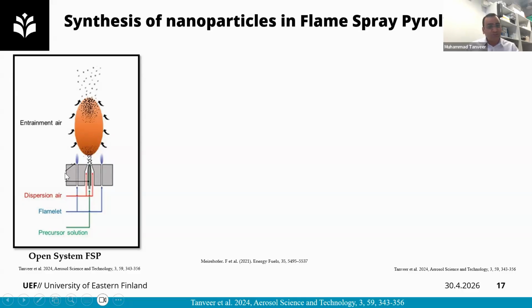Due to this oxygen and the highly reactive, high temperature atmosphere, different gas phase products start to be produced. When the gas phase product concentration is quite high, they become supersaturated, and this starts to form nuclei of nanoparticles like carbon dots or metal oxide, whatever we are producing. After that, these nuclei undergo homogeneous and heterogeneous nucleation, and the particle size grows further through condensation and nucleation stages. Following this, downstream of the flame, the temperature decreases due to the entrainment of air. So these nanoparticles agglomerate and transform into aggregated structures.